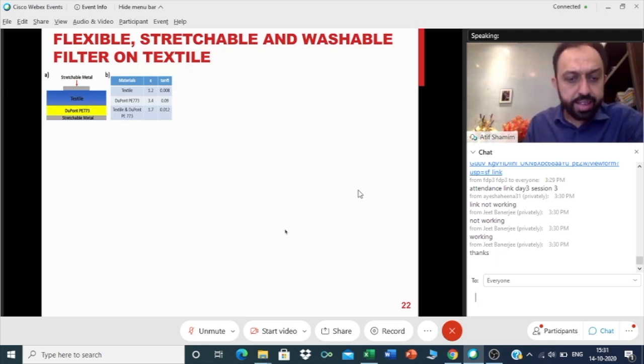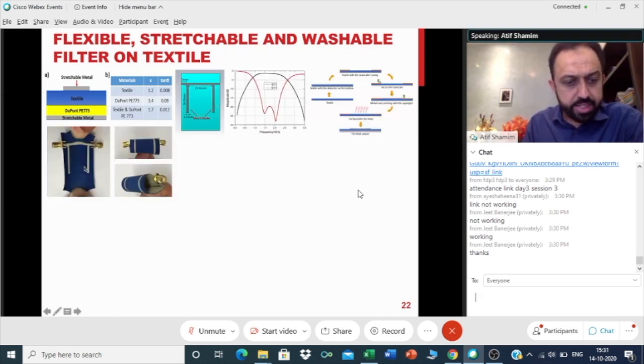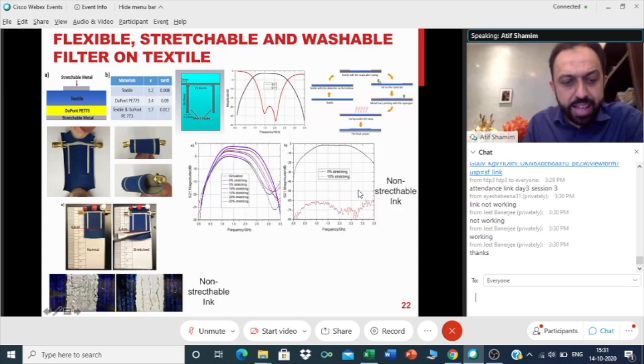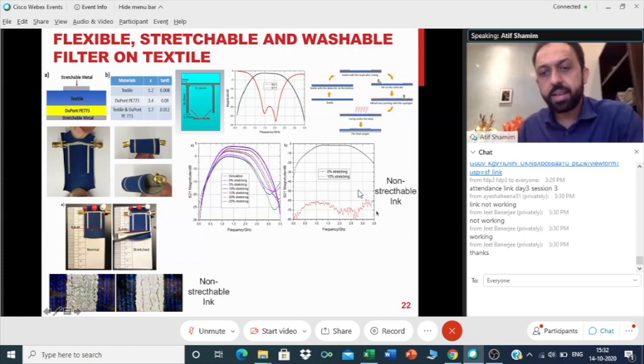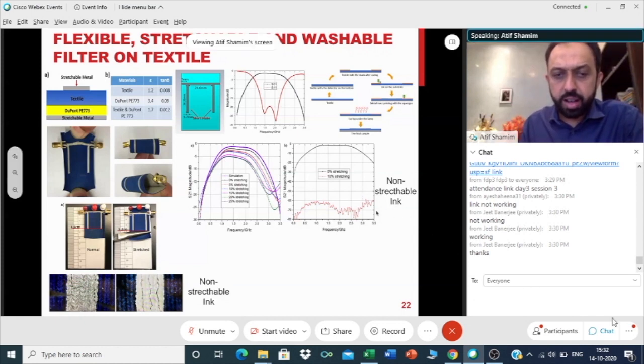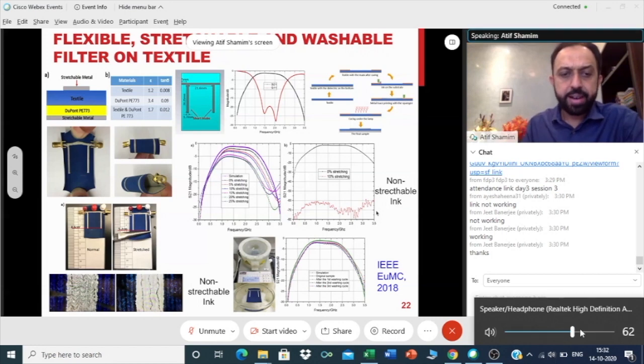And we saw that we could stretch the ink up to almost 30%, which is the typical stretching limit of a wearable T-shirt. You could see that the non-stretchable ink develops permanent cracks, whereas the stretchable ink does develop some cracks, but as soon as you release it, the cracks are filled up again. So it could work. The performance is deteriorated a little bit, but it could still work up to 25 to 30% of stretching, which is the limit. The non-stretchable, as soon as you stretch it one time, that's it. It's gone. It doesn't work again. You have permanent cracks there. So this was good stuff which we did in terms of wearable antennas and all that.